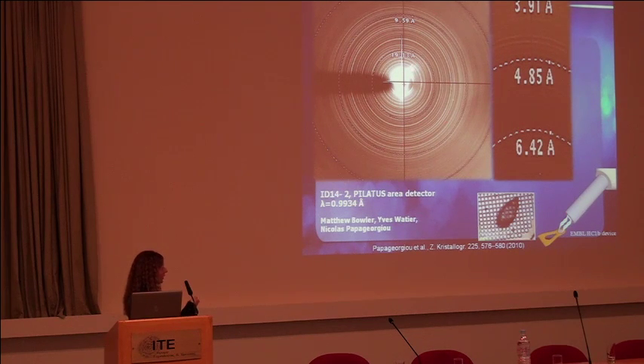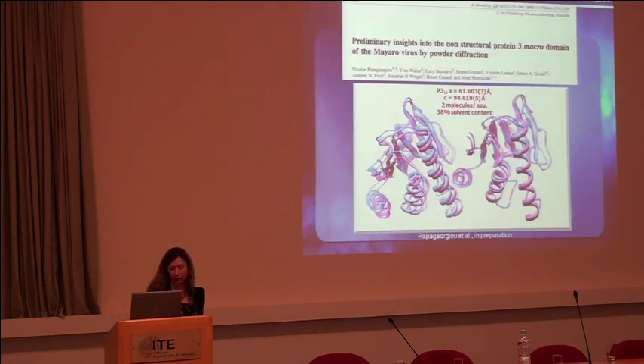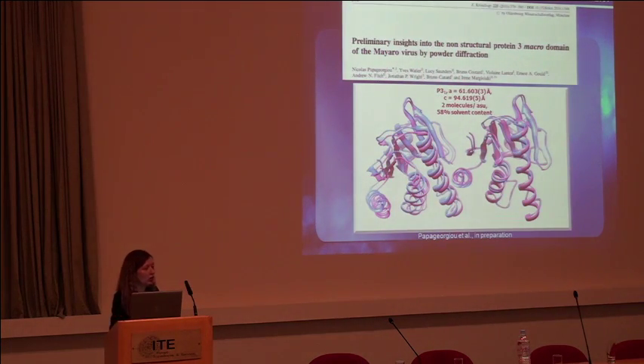By the way, in order to have good data, you need to see homogeneous rings, otherwise the intensities will be wrong, and you cannot do anything further than indexing. We collected this data at room temperature using this controlled dehydration device, and with this resolution we could even solve and refine the structure of a 120 amino acid domain of a virus protein. The protein is non-structural protein 3 of the virus. The structure was unknown to date, and now we are preparing the first structural model to be released very soon.